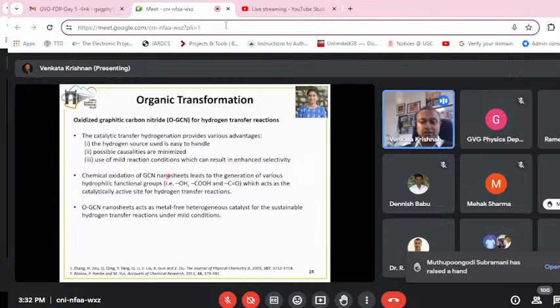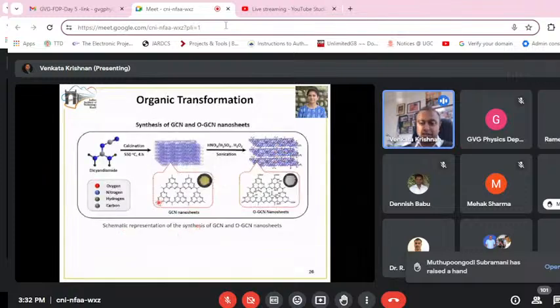So what we have done is we have taken the graphitic carbon nitride, the same material introduced earlier, and performed a chemical oxidation on it. This oxidation process introduces OH groups, COOH groups, or carbonyl groups onto the material, and these are the active sites that carry out the transfer hydrogenation. This oxidized form of graphitic carbon nitride was used as a metal-free heterogeneous catalyst for sustainable transfer hydrogenation under mild reaction conditions. This is how the material was prepared.